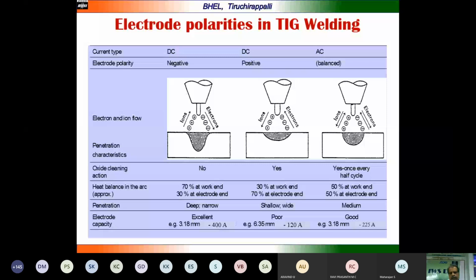With AC balanced, 50% of the time it is DC electrode positive and 50% electrode negative, so both benefits can be obtained. 50% of the time the job gets cleaned, and 50% of the time the welding can be done. Heat input is also distributed equally between the job and the electrode, the penetration is medium, and for a 3.18 mm electrode we can use up to 225 amps current. This is how TIG welding has versatility, and we can use AC for welding aluminum, which can get oxidized. So this is a clean welding process.